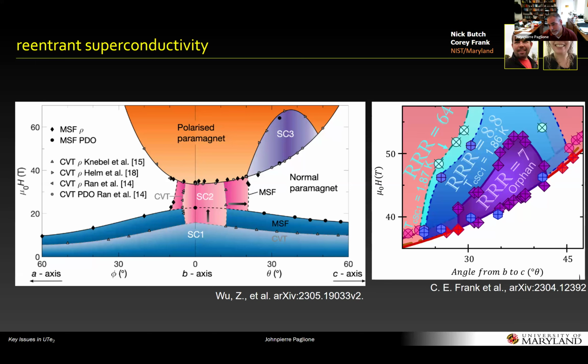You know, the polarized phase has an interesting temperature evolution, just to make sure you're aware of that. So it's a very sharp transition at low temperature, but as you warm up, that kind of smears out, and by about 20 Kelvin, which is believed to be the onset, it's almost gone. You know, for instance, if you measure a magnetic signal or transport.